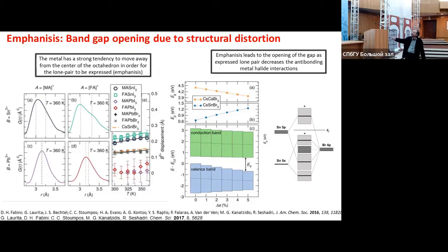And to do this, we had to do total scattering experiments, to try to correlate direct space with possible deviations from the original position. So we're looking at the movement of the central atom of the octahedron from its position at the center of the octahedron. And basically you see that there is some shifting. We see a peak, a shoulder happening at a different distance between the metal and the halogen. And it varies for every perovskite we selected, from close to 0 when we're on the lead side, to large deformation when we go to other metals, especially tin, and different cations.